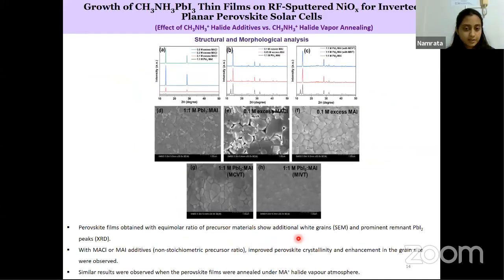Here is the result for all these conditions. Talking about figure A and the corresponding ones, when we change the amount of methyl ammonium chloride, we can see a clear difference in the peak intensities of the characteristic peaks. Similarly, if we compare all the other conditions, we can see the variations. From these figures and the XRD image, we see that the best film was obtained when the MAI to PbI2 ratio was 1:1 and annealing was done under a methyl ammonium chloride vapor atmosphere.